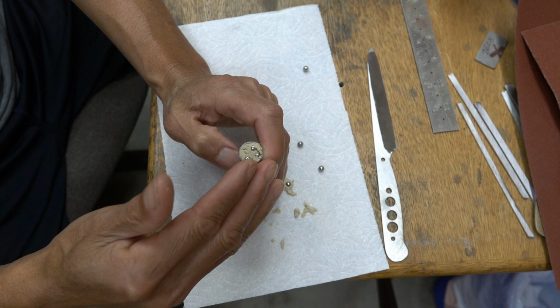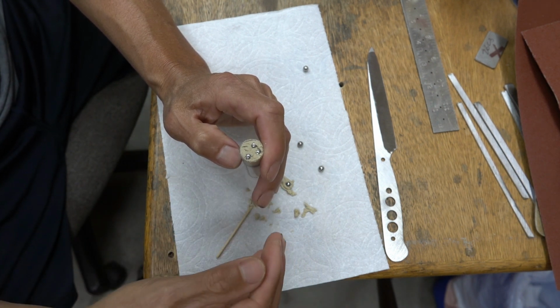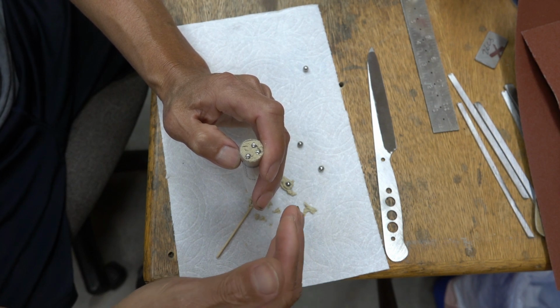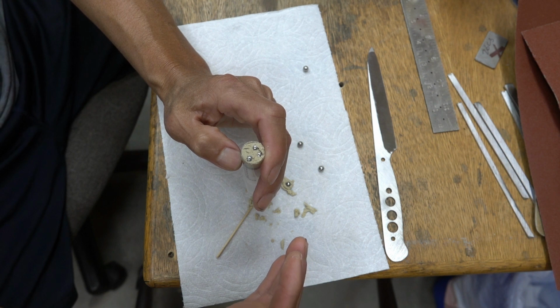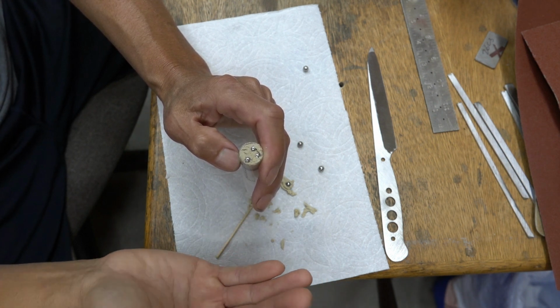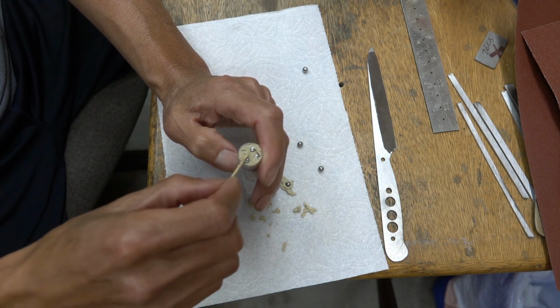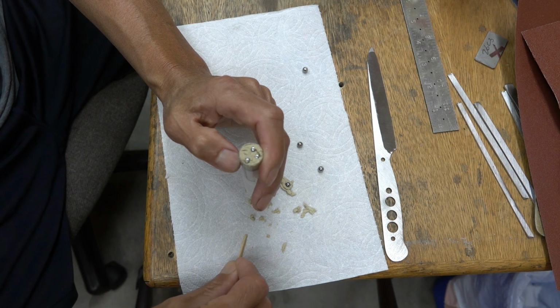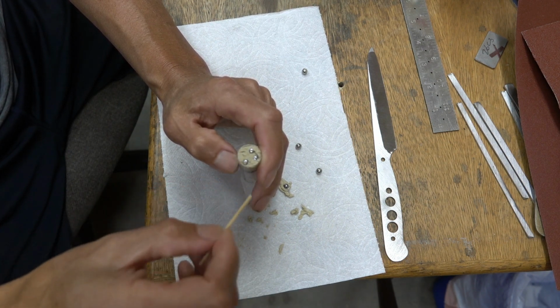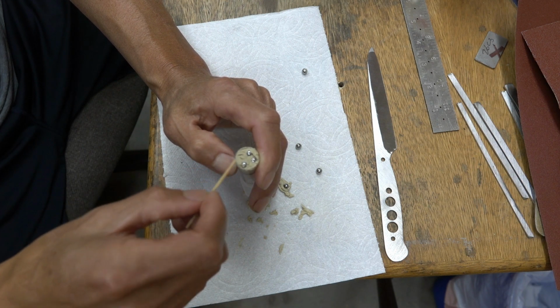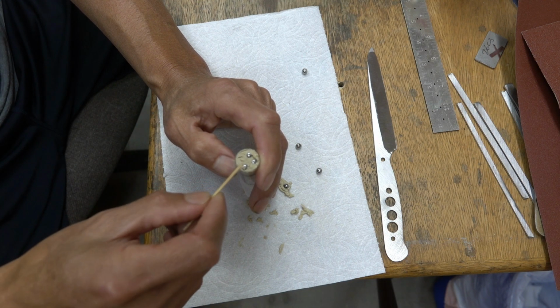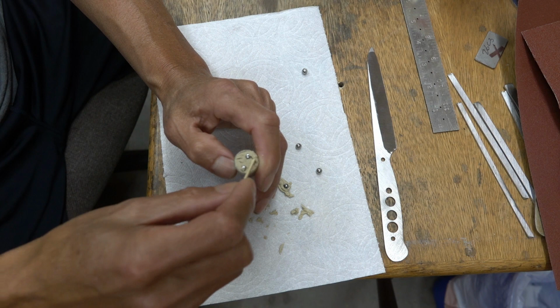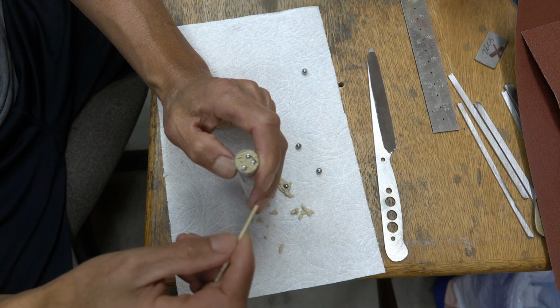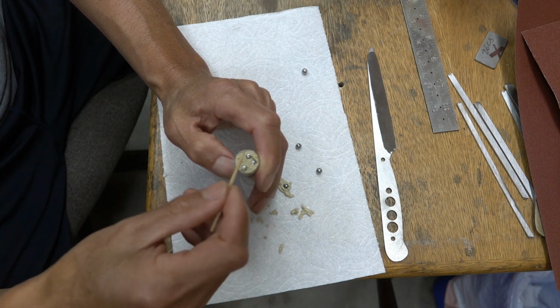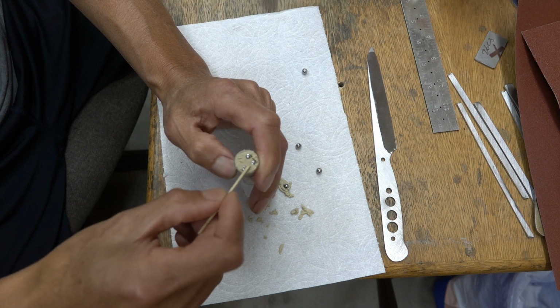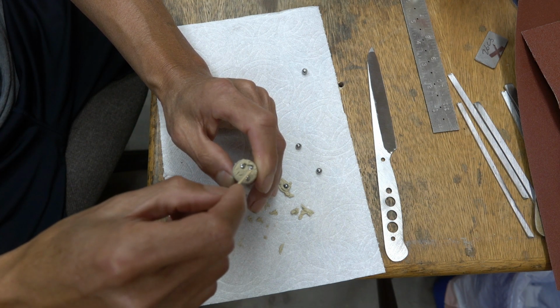Side to side comparison means the steel got heated up at the same temperature, soaked for the same length, and then tempered at the peak hardness. So they are at peak hardness, and we put them side to side and see what happened to the surface. From the optical image, I see plenty of evidence, with enough resolution to see this qualitatively. Also, when you count carbide, you can see some quantitative results, depending on the abrasive and the different setup. You can count carbide, and you can see how much surface loss there is.